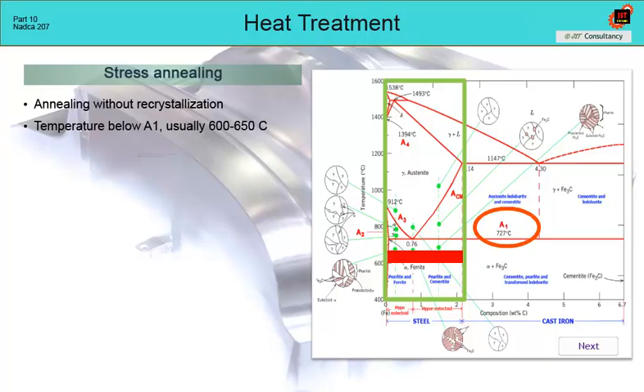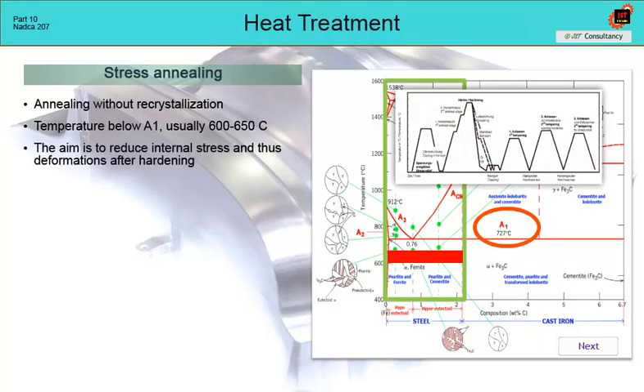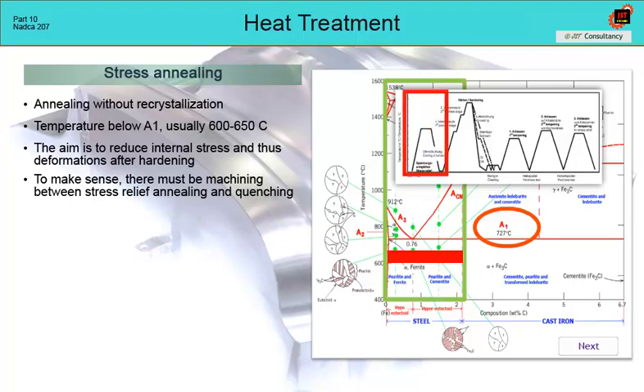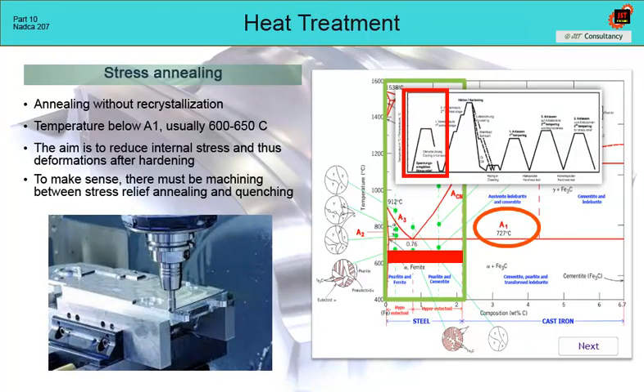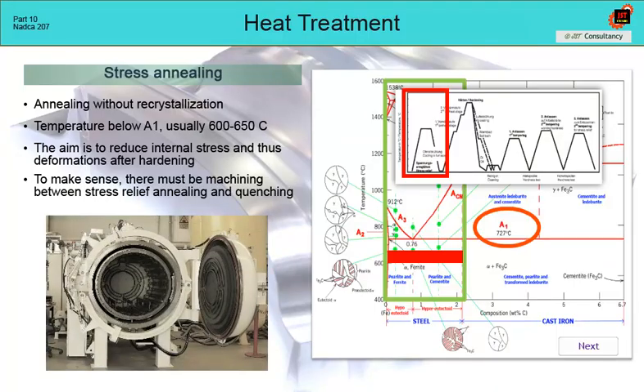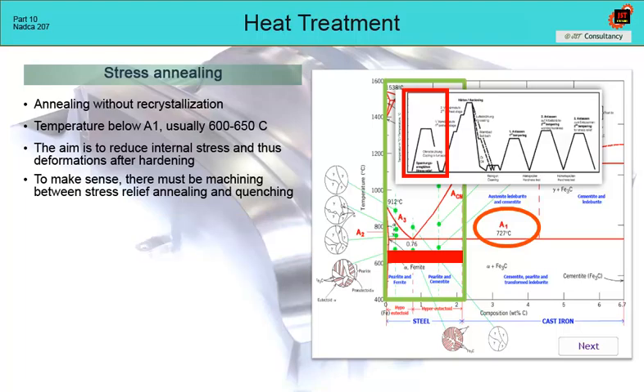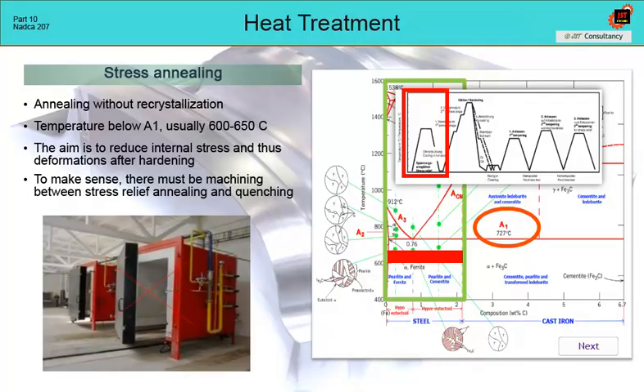The aim of this annealing is to release the internal stress after roughing the material and thus stabilize the shape of the insert before the quenching. After stress annealing and before quenching, fine machining must be included, with final additions for quenching. Annealing should take place in a vacuum furnace or under a protective atmosphere. If it is carried out in air, surface decarburization and oxidation along the grain boundaries must be taken into account. In this case, it is necessary to remove at least 1 millimeter from all surfaces of the insert.